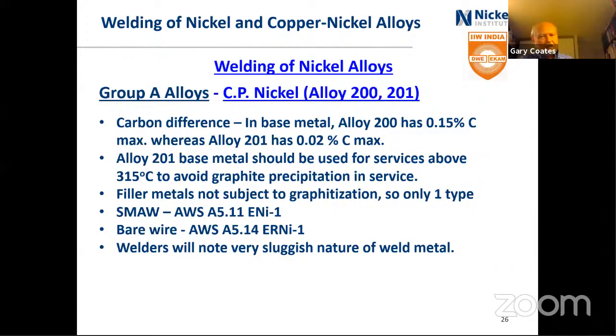The carbon in the nickel alloy is there to give it a little bit higher strength. We saw earlier it's a very weak alloy. Trying to get a little higher strength out of it, typically it will have a higher carbon level.